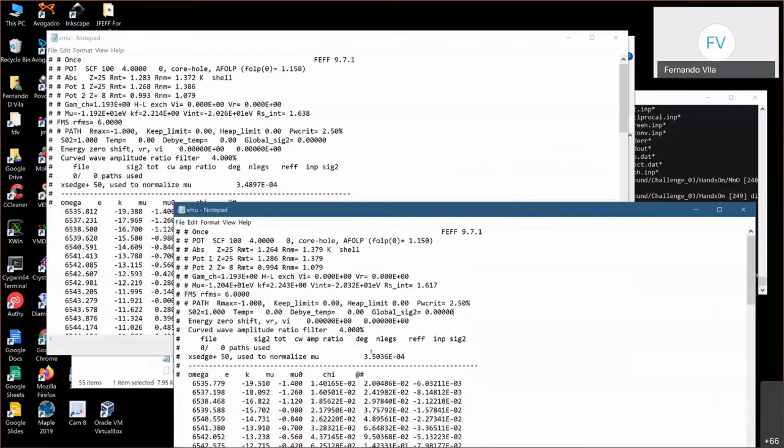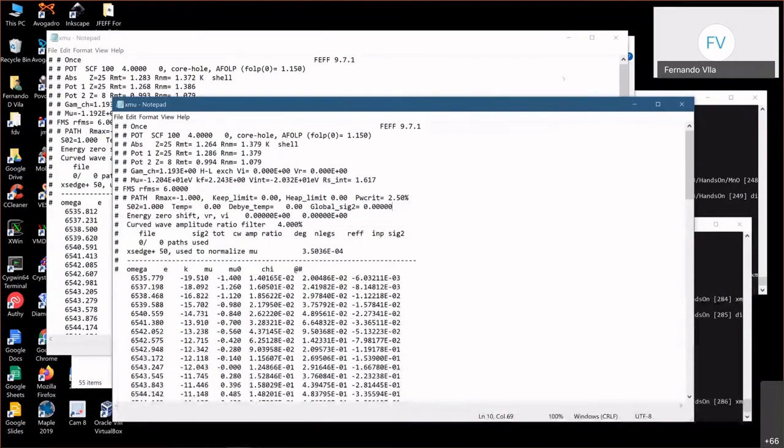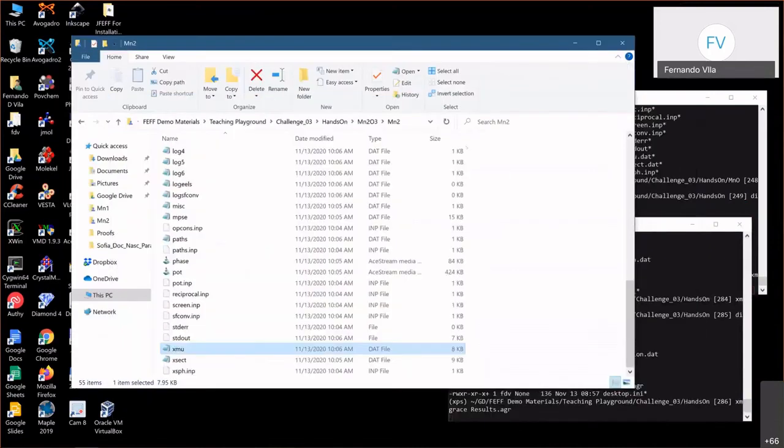But there are certain cases in which the normalization factors are slightly different between the two cases, and you want to have them exactly the same. So your two options are either you run your calculations with the absolute card and get results in absolute units, or you do your calculations and get normalized results, and before you do the averaging, you take into account the normalization factors, by multiplying your intensities by these numbers before you do your averaging. So that's a way to do it. Thanks for reminding me of that, Josh.